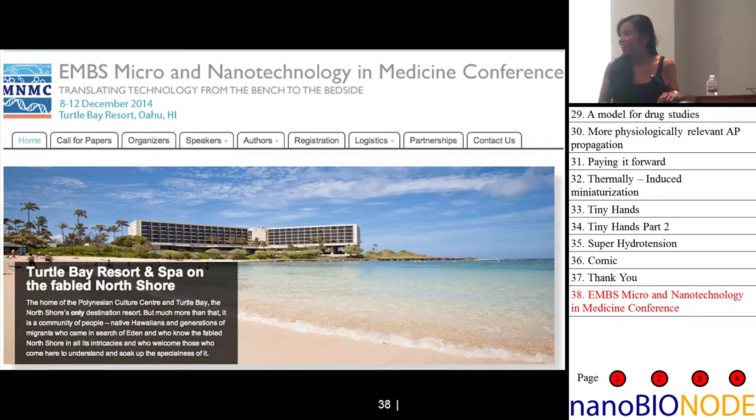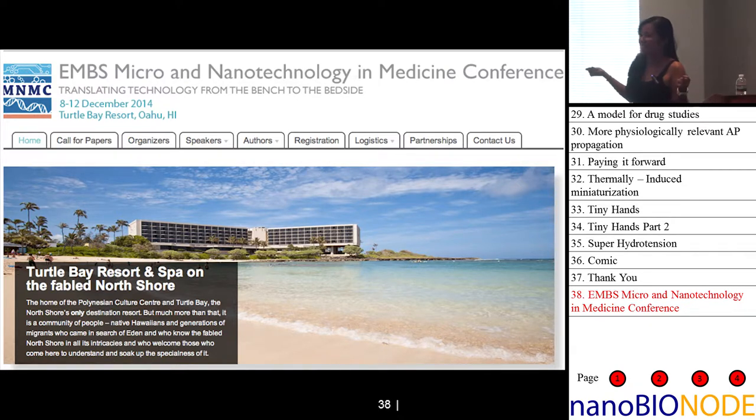I have a question. So what sets the limit of how much something can be shrunk? It's how much the film is extruded in the first place. So the polyolefins are blown out. So they're pulled, stretched out, like a rubber band basically. You stretch it out and then freeze it in that configuration so it'll shrink back to its relaxed state. So however far you can extrude it. And it's also a function of the molecular length of the polymer. So kind of the limits of that.